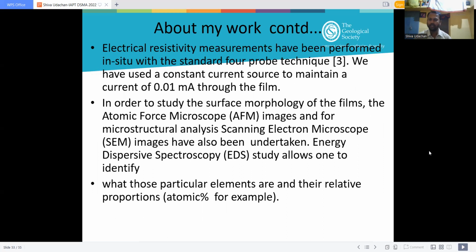Electrical resistivity measurements have been performed in situ with the standard four-probe technique. We have used a constant current source to maintain a current of 0.01 milliampere through the film. In order to study the surface morphology of the films, atomic force microscope, AFM, images, and for microstructural analysis, scanning electron microscope images have also been taken. Energy dispersive spectroscopy, EDS, study allows one to identify what the particular elements are and their relative proportions, that is, atomic percentage, for example.